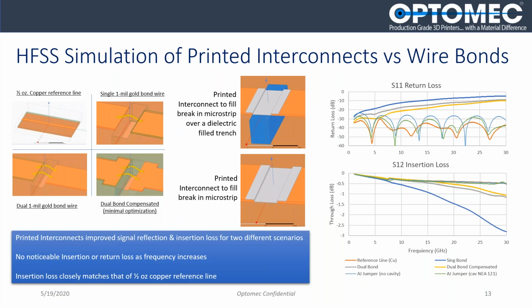This is just showing some high-level HFSS simulation of printed interconnects versus wire bonds, to try and showcase the signal performance improvements at a theoretical level that are achievable by using a properly shaped, impedance matched printed interconnect versus a wire bond, or multiple wire bonds, or even dual compensated wire bonds that are sometimes seen inside of millimeter wave packaging. And as you can see in the diagrams on the right, the printed interconnects really start to operate more like the transmission line or the coplanar waveguide that the connection is being made to and from.